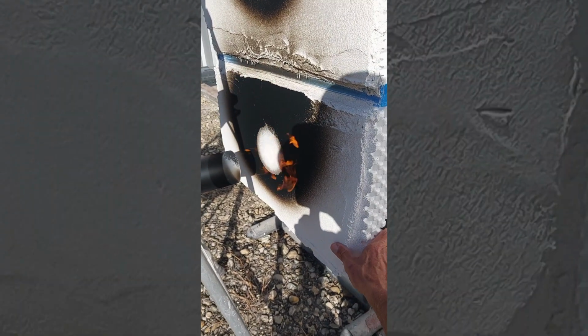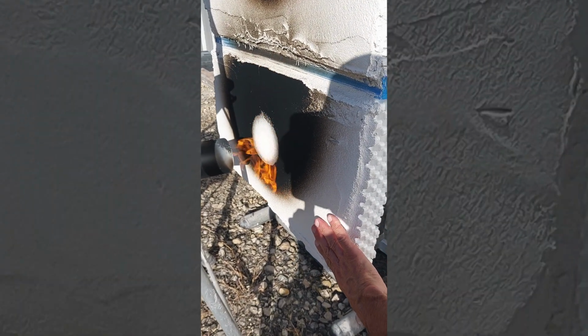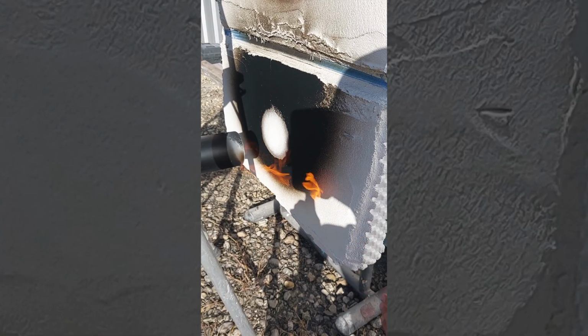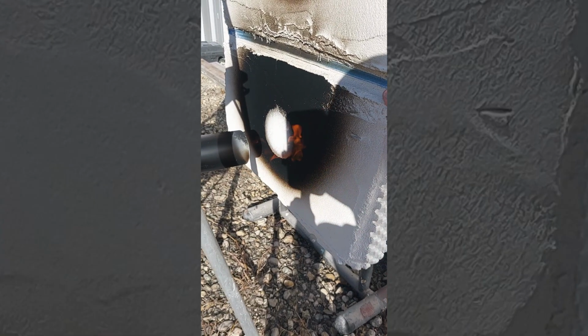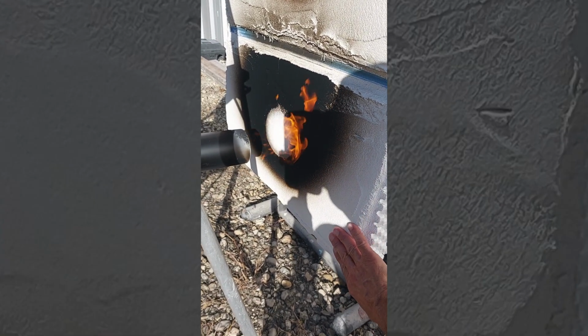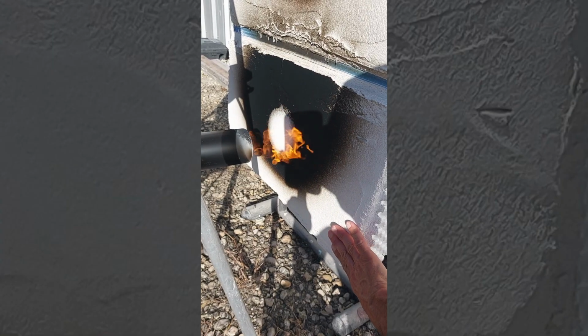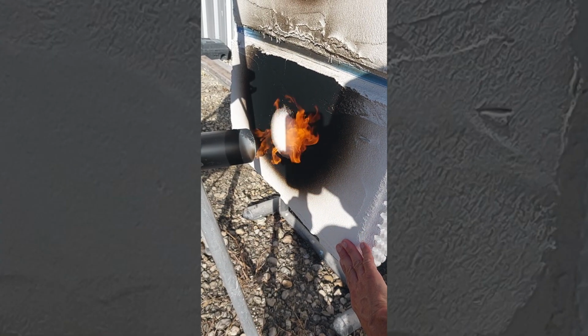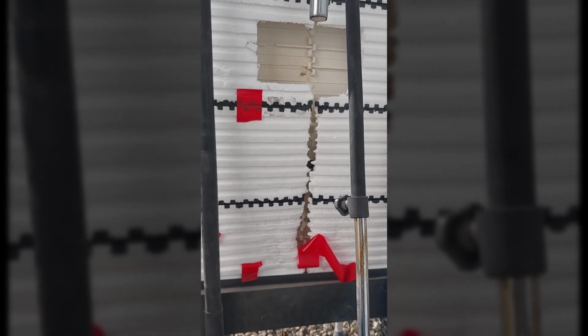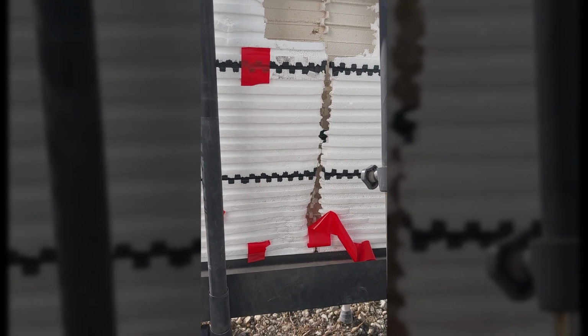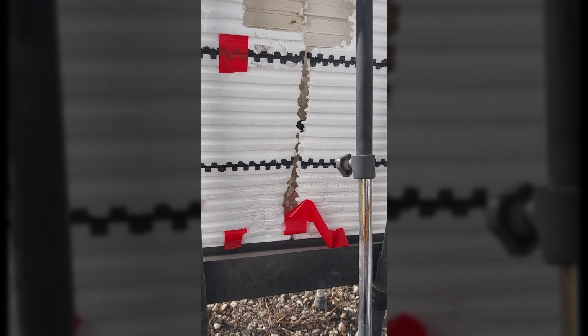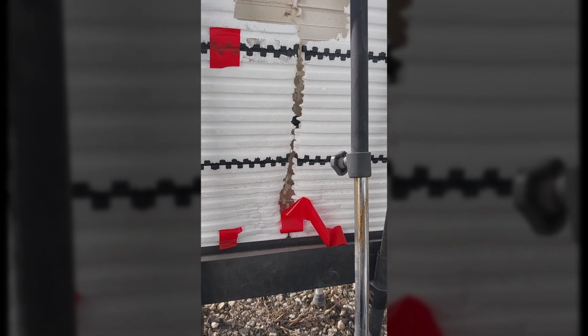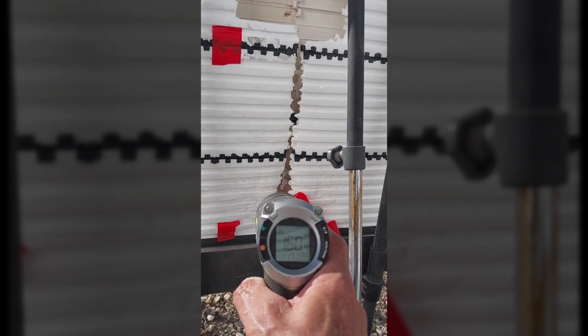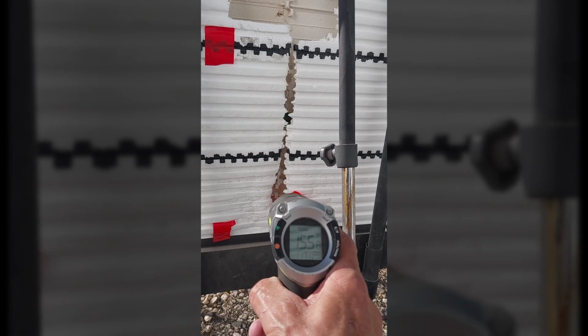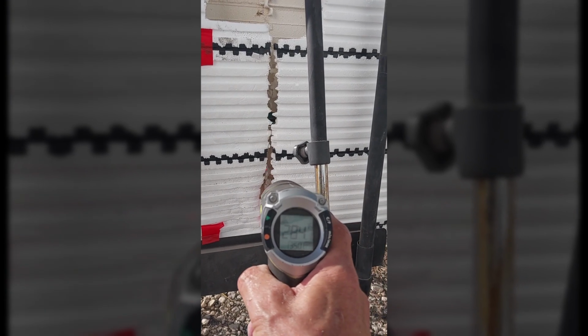Interestingly, the BioLime coating itself is cool to touch. Being careful to avoid the flame, one can even place their hand on the surface adjacent to the flame without feeling high heat. The material shows no signs of degradation or delamination. On the back side, we see very minor deformation of the styrofoam. Our red tape still has not melted or fallen off. The temperature readings are consistent with what we've seen in previous readings, measuring from 150 degrees at the seam to 275 degrees in the cavity.